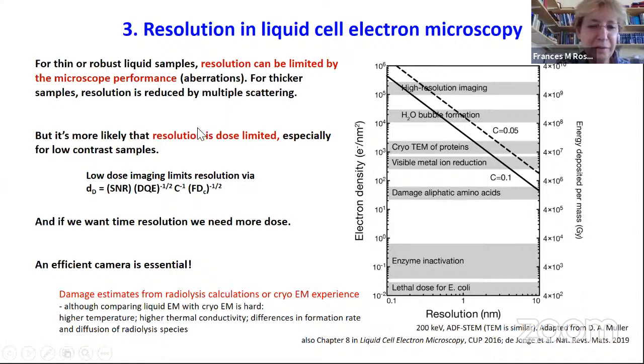And so we typically, like the biologists, have to think about dose limited resolution. And that leads to graphs like this, where you say, what is the damage threshold for certain types of materials, and what kind of image resolution could you get if you can only use this many electrons to form the image. And so you often find that understanding what limits your resolution is a very important aspect of the experiment, because if it is dose limited, you really have to use low dose techniques. And if it's not dose limited, you can then go and use a higher dose and get a nicer looking image that would have a better resolution.